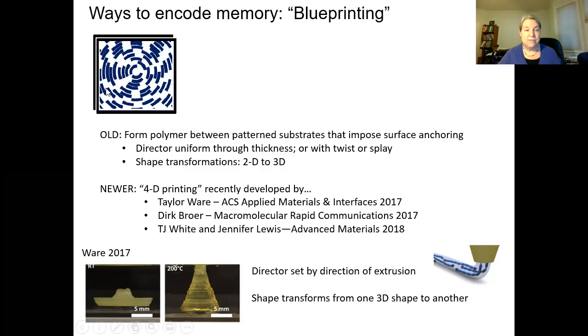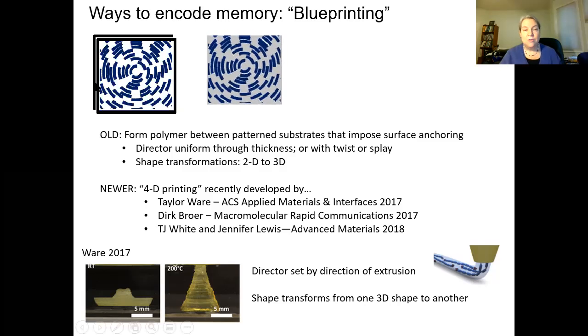And then if you take it out of the glass, and hopefully that will work, then you get a piece of polymer that has that same liquid crystal orientation field, what we call the director field, uniform through the thickness. Of course, that depends on the cell not being too thick. And then when you heat it, it will transform into whatever shape. And considering that it has the bullseye pattern, it would make a cone. And so you get essentially a three-dimensional object.